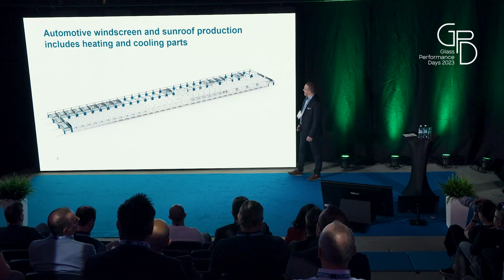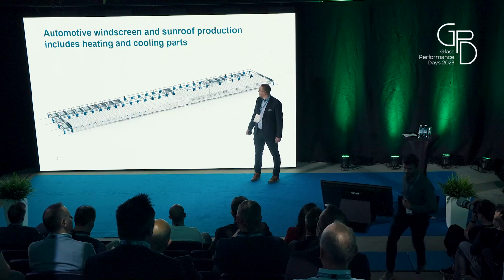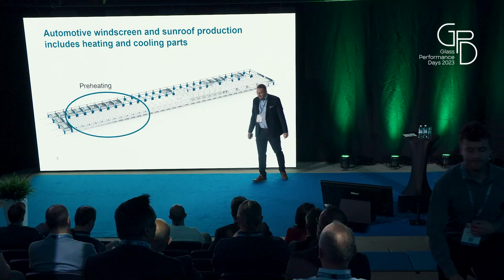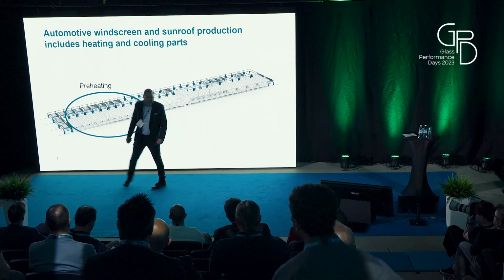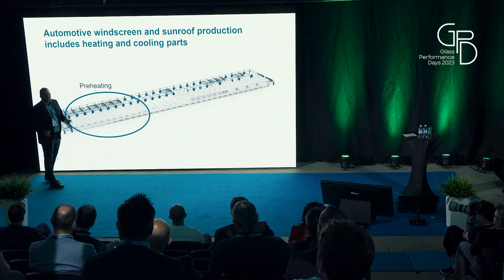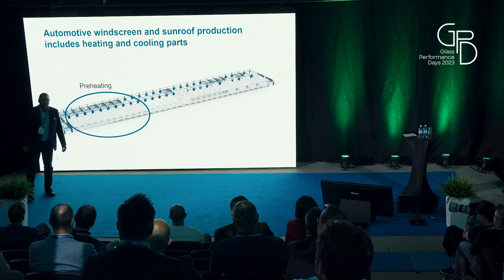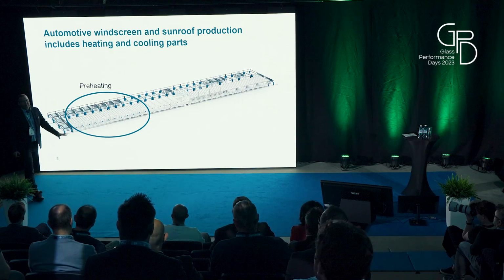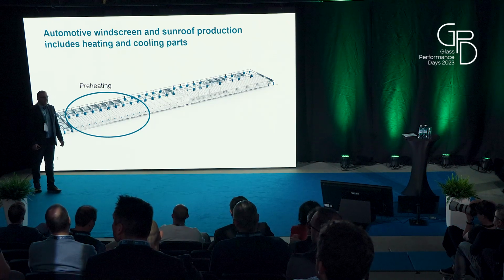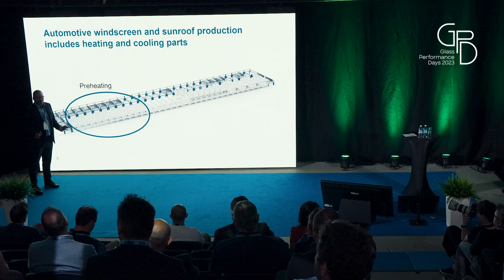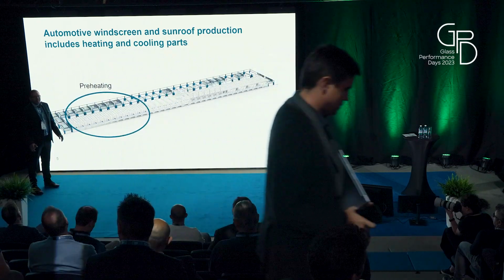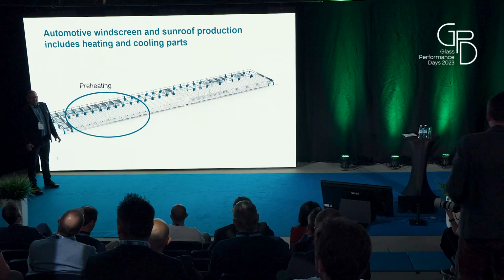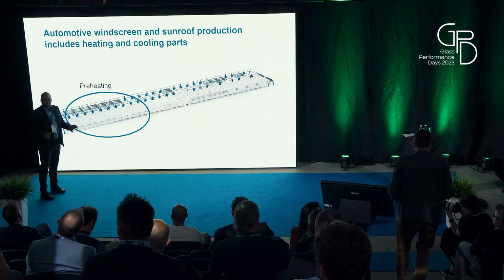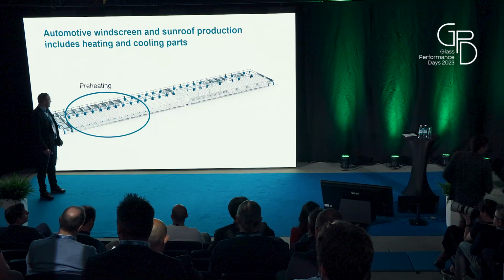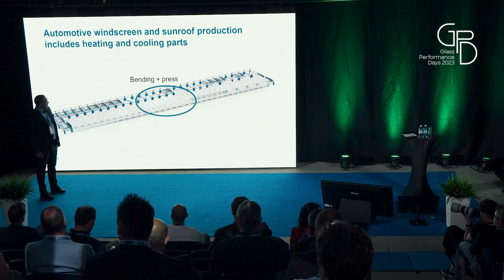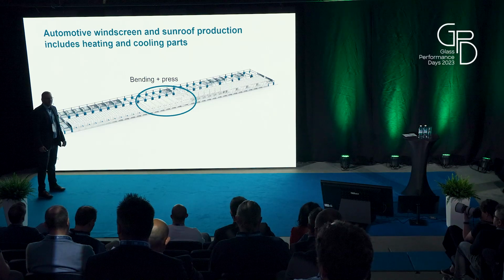Some of you have seen an automotive windscreen bending line. There on the right side, or on your left side, there is a preheating part, which is my main thing where I will concentrate today. So in that part, the idea is that the glass is heated up to 500 degrees, and the target is that after the preheating part, glass is at as uniform a temperature as possible. We can do this quickly and make it good for the bending process where the main bending is done.